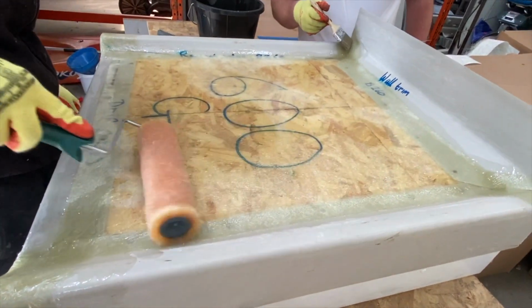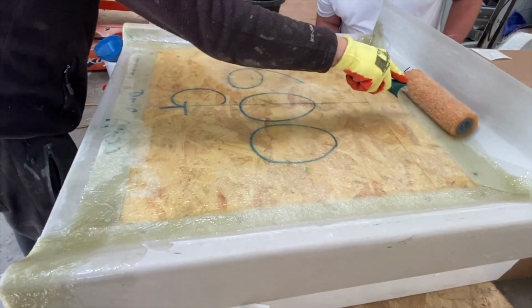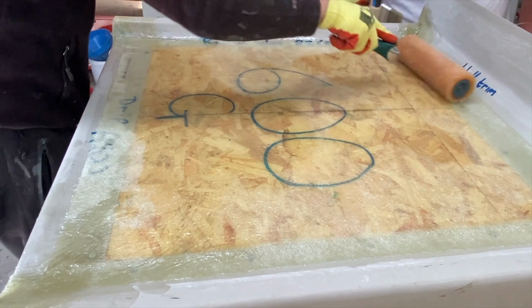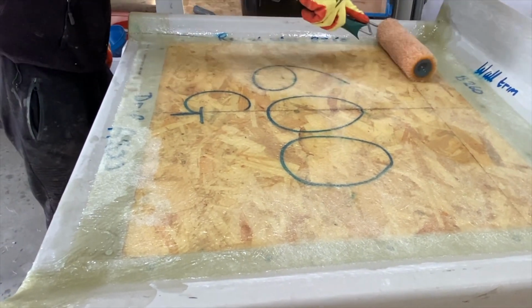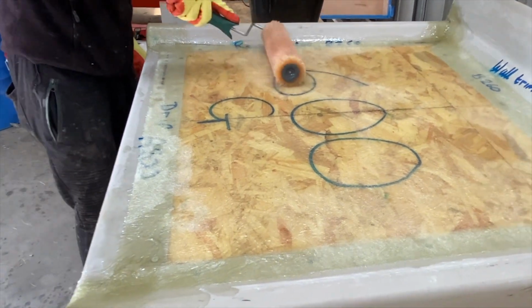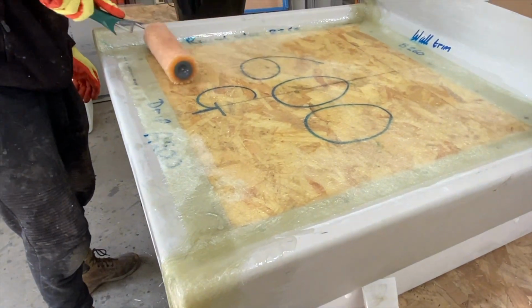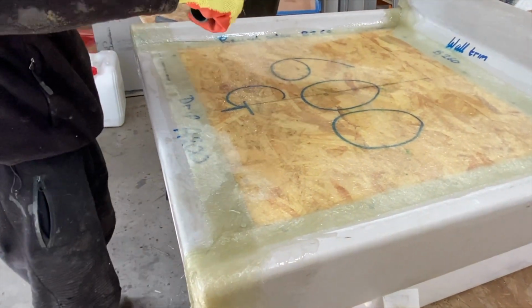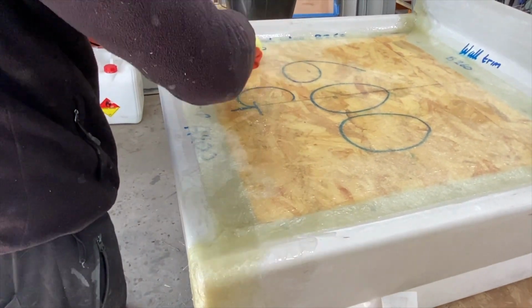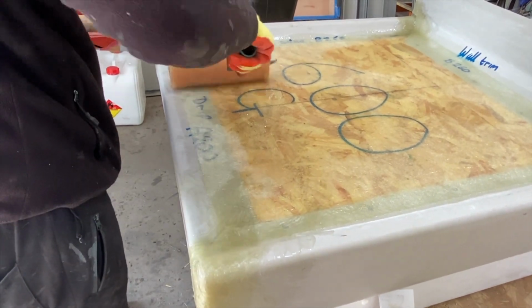You should expect to see a colour change. The matting should turn from white colour to an almost see-through, slightly brown coloured surface, and you can clearly see that the timber underneath is visible. When dealing with overlapping sections of matting, ensure that there's an overlap of around 50 to 100 millimetres to ensure that the laminate is completely seamless.